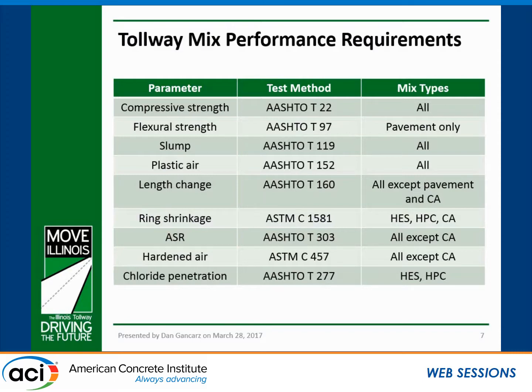And then we have our shrinkage testing. So we look at length change for all our mixes except pavement and calcium aluminate. We evaluate ring shrinkage on more of our high performance mixes, which is the high early strength patching, the HPC, and the calcium aluminate patching mix.